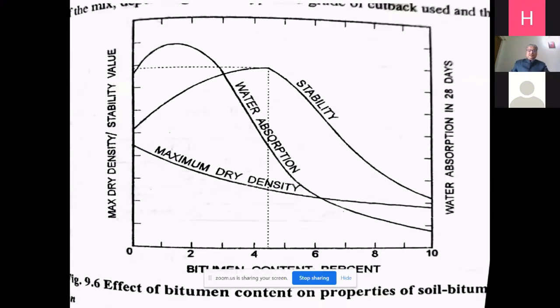You can see here, as you are increasing the bitumen content, the stability first increases up to a certain point, but then it starts decreasing. That is why I said that bitumen content is also important. You cannot go on increasing infinitely, because the bitumen is weak in the stability itself, but its role is to provide the waterproofing and the cohesion or the adhesion between the aggregate and the bitumen. So that is why up to a certain point it goes on increasing, then it starts decreasing.